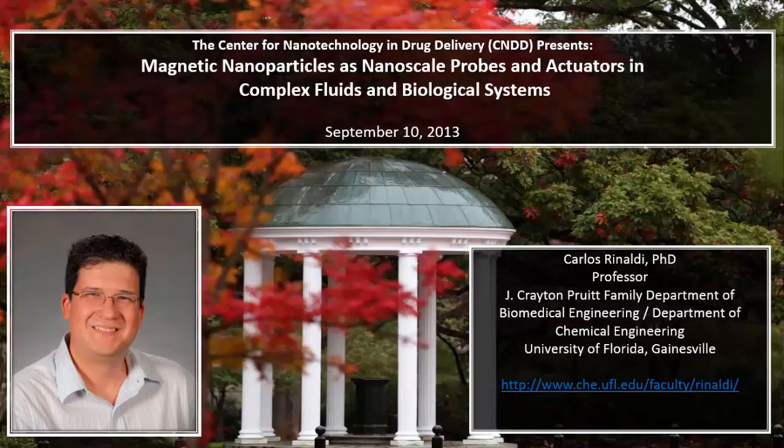And the reason I'm pointing that out is, one, it's going to be important in some of the things that I'm going to work on, but it also illustrates the importance of knowing what you're doing, obtaining particles with known properties, obtaining particles with narrow size distributions. I'm not going to go into the details, but the point is that if you have polydispersity in particle size, if you have aggregation, you most likely are going to have a combination of the two mechanisms of relaxation or response to magnetic field.